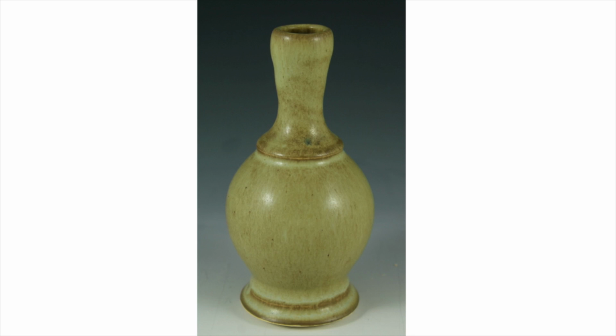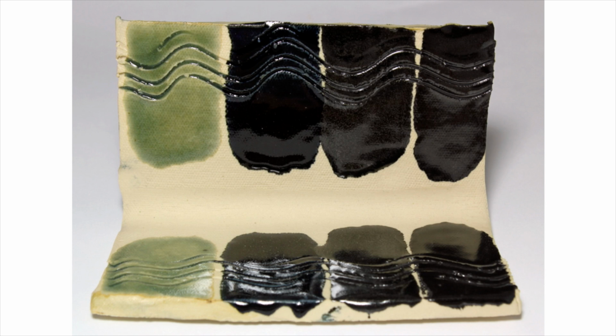I had another one to change the color of an already mixed up wet batch of glaze. I added 1 to 5% increments of metallic oxides—or you can use commercial stains—and do the same testing procedure. I wanted a black glaze, so I tested a 500 gram batch of slop glaze, exhibited here on the far left stripe, and then added increments of cobalt carbonate.